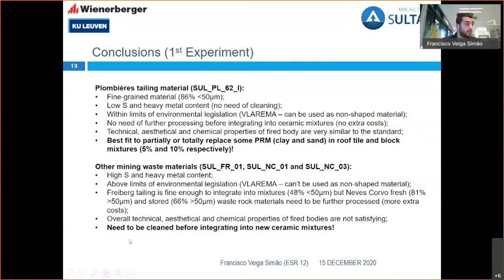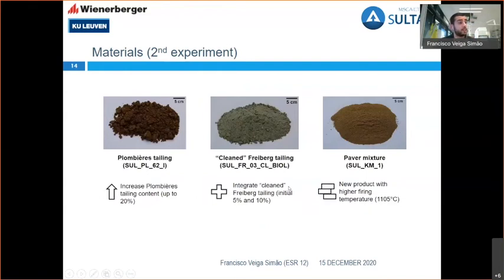All the other ones indeed present exceedances. Even though Freiberg is a fine tailing material that can be integrated straight away into the ceramic mixtures, it has a lot of sulfidic content, which also gives bad results on several other properties. So there is a need for this mining waste to be cleaned, and it's exactly that which my ESRs, my researcher colleagues at Sultan, already provided me with. I not only increased the Plombières tailing content on my ceramic pieces, but I also started using the clean Freiberg tailing at the initial 5 and 10%, 5 in roof tiles, 10 in blocks.